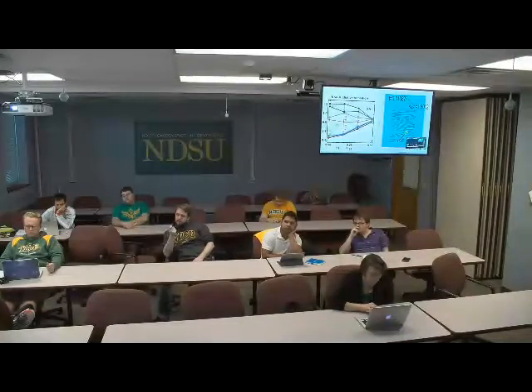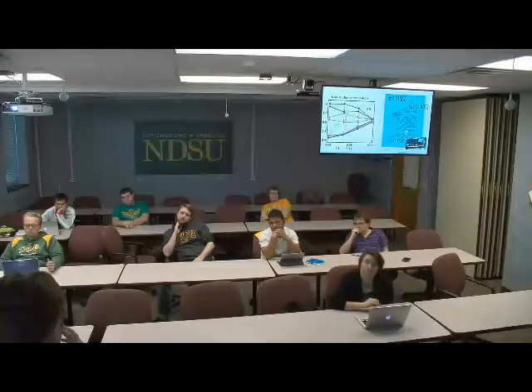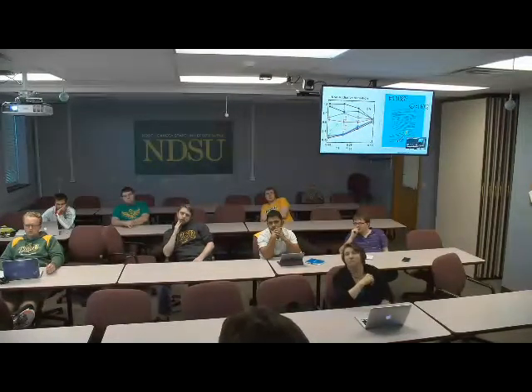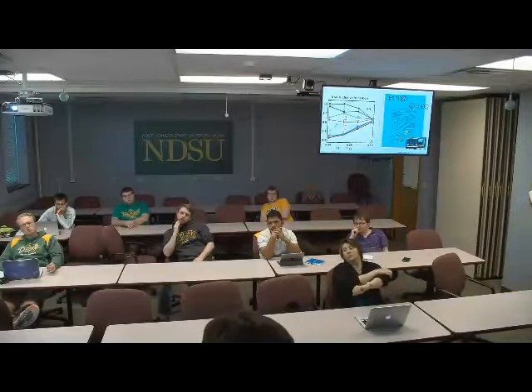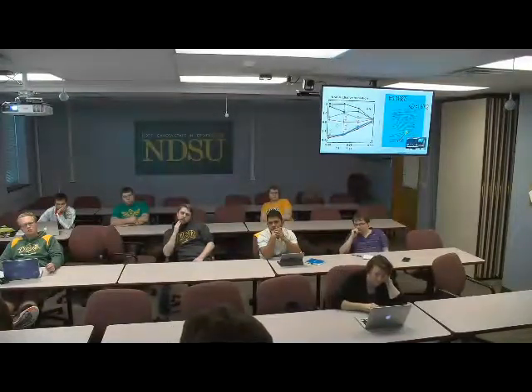So the challenge in this work was to take into account transitions which either conserve momentum or violate conservation of momentum. Violate not in the sense of violating the rule of momentum conservation, but that momentum departs from the electronic subsystem and is transferred to the subsystem of nuclear degrees of freedom. So the electron was moving, it stopped moving, and then a nucleus or a set of nuclei started moving. We are focusing only on the electronic degrees of freedom, therefore we allow transitions with local violation of momentum conservation.